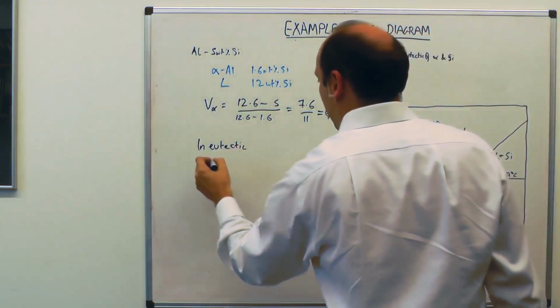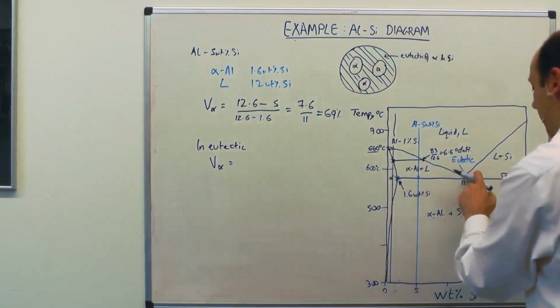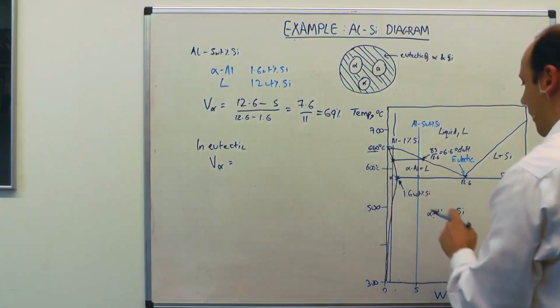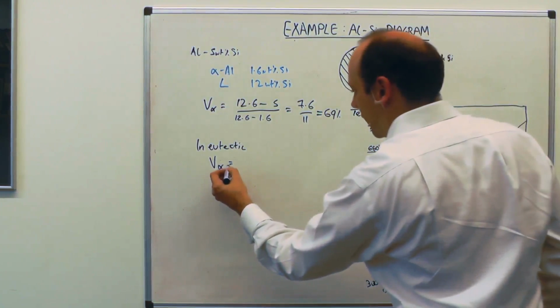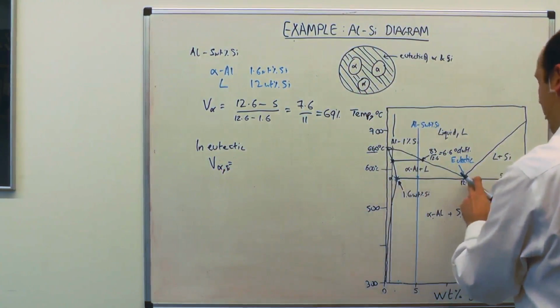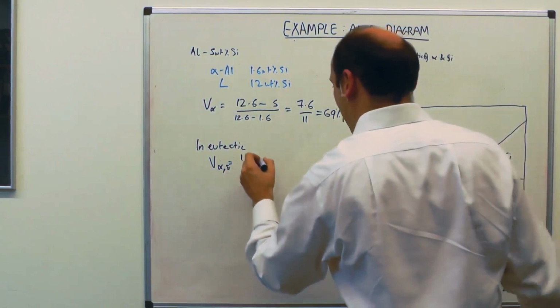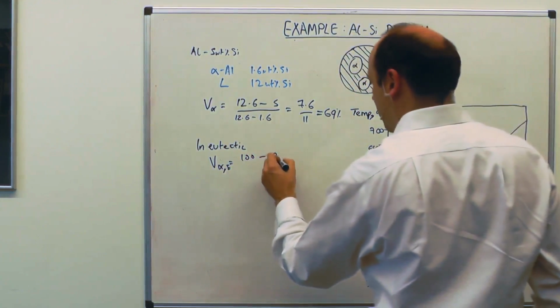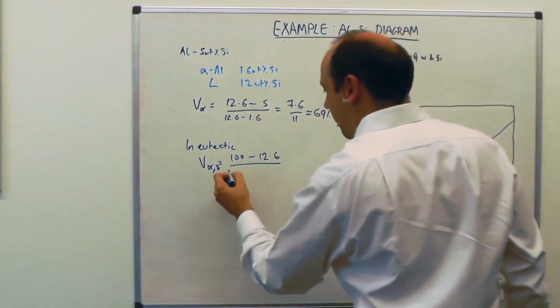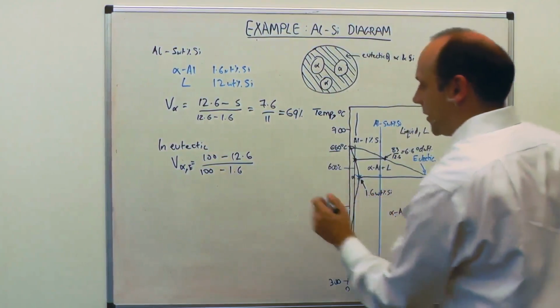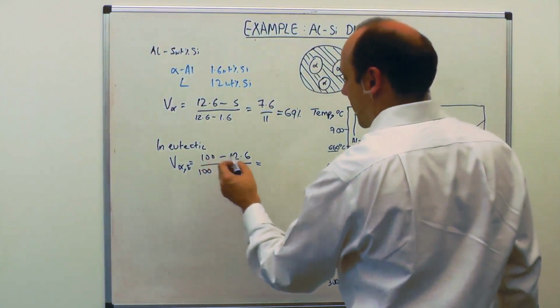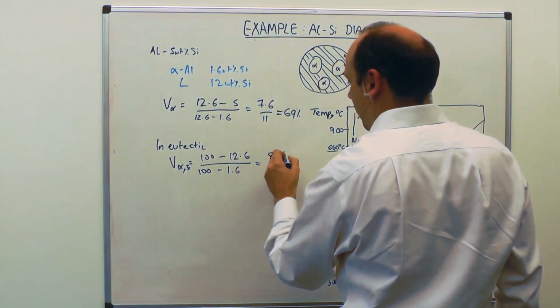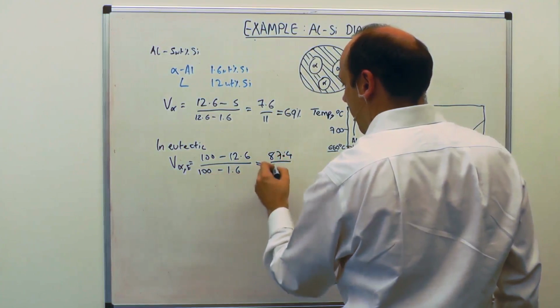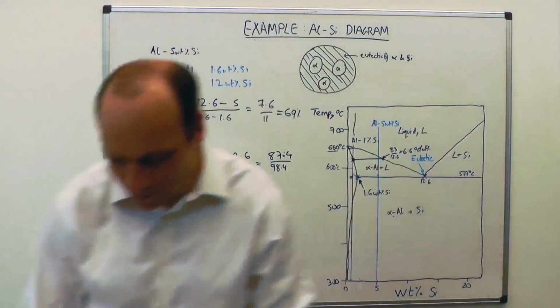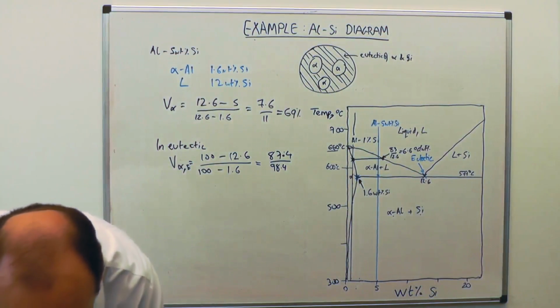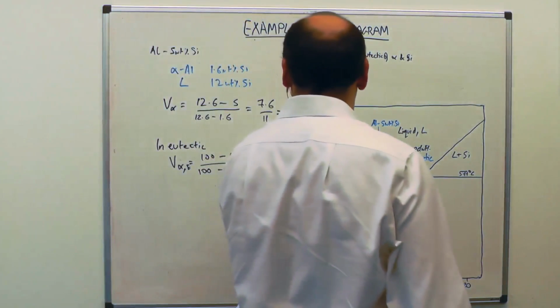In the eutectic, the volume fraction of alpha will be, we've transformed this liquid into alpha and silicon. If you want to know the volume fraction of alpha in the eutectic, then it's the opposite little distance. So that's 100, because the silicon's all the way over there, minus the liquid composition, that's 12.6, divided by the whole distance, which is 100 minus 1.6, because that's our solubility in the alpha. So that's 87.4 divided by 98.4. That's 89%.